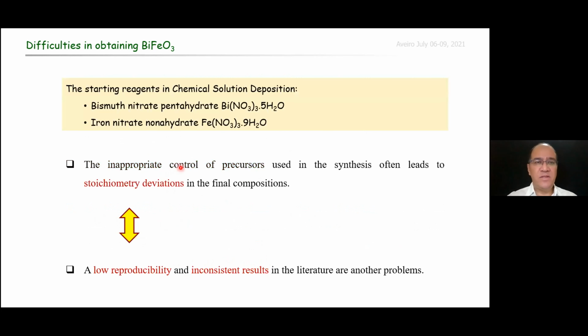Regarding the inappropriate control of precursors, it is important to note that the bismuth and iron nitrates often used in chemical solution deposition are highly hygroscopic. Then the inappropriate control of these precursors is a critical problem of stoichiometry deviations in the final composition that must be considered during the film synthesis. All these difficulties lead to low reproducibility and inconsistent results in the literature.